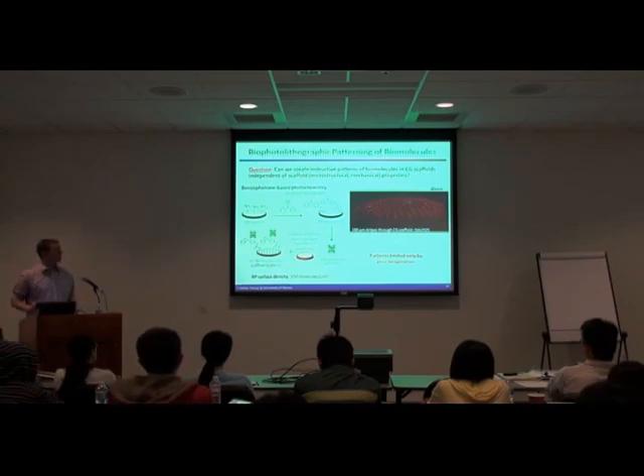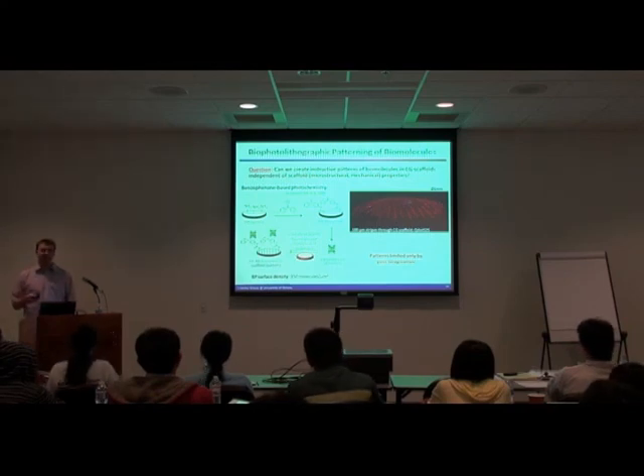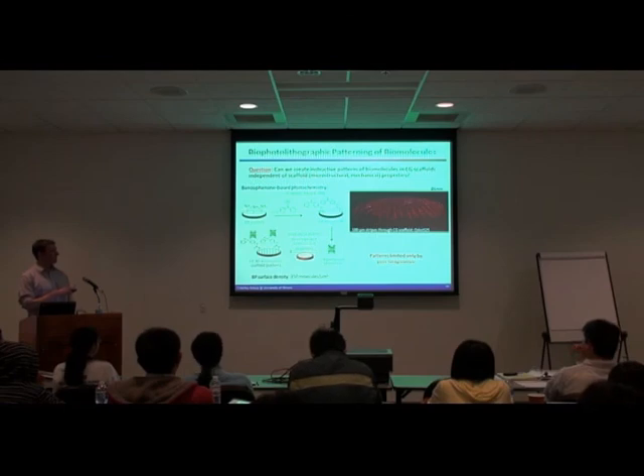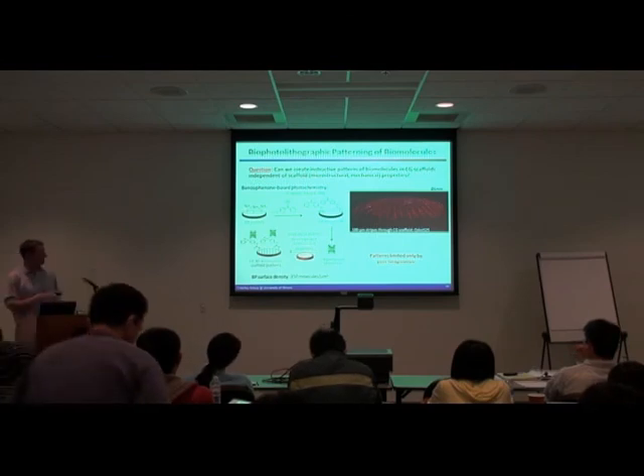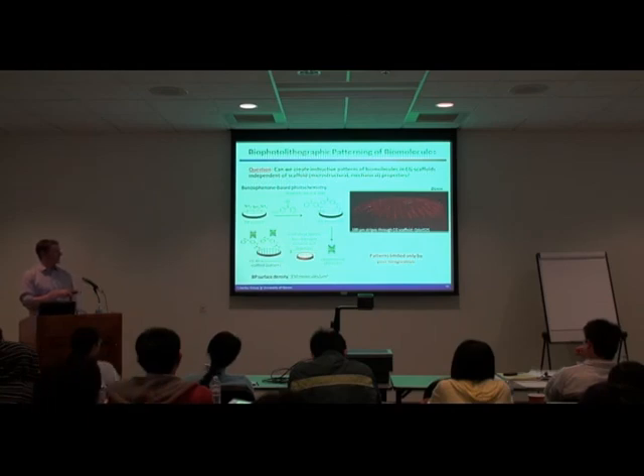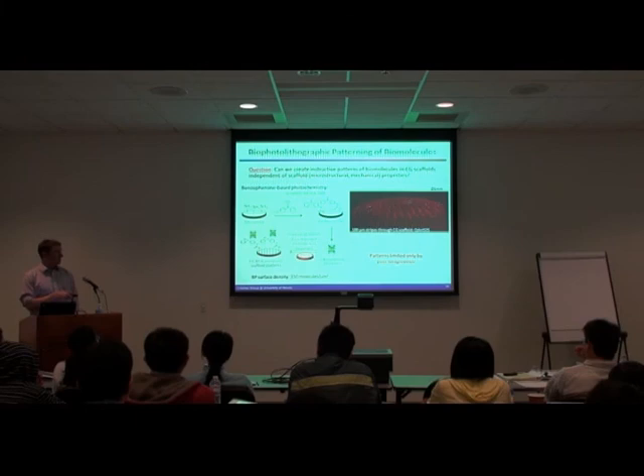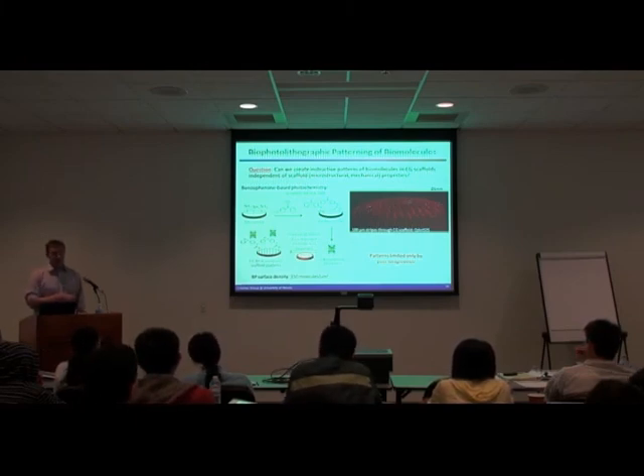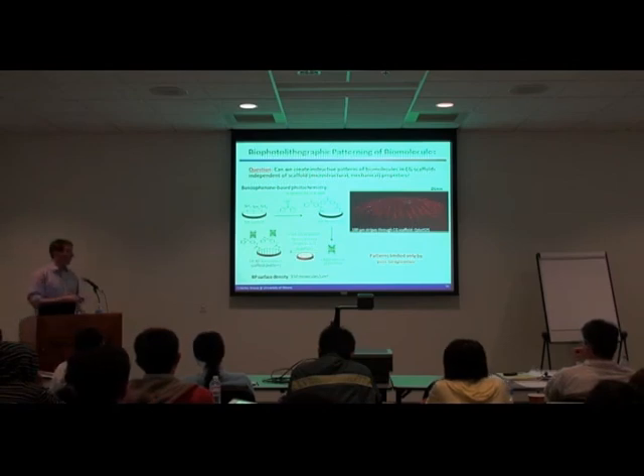This is the biomolecular aspect I didn't want to go into very much, but we can take our collagen GAG scaffolds and use a benzophenone photochemistry approach. We're working on this with a colleague here in Biomolecular Chemistry, where we take our scaffold with defined microstructure and mechanical properties, and attach onto the scaffold, through the free amines on the collagen surface, this benzophenone molecule. The interesting thing about benzophenone is that when you irradiate it at 365 nanometers, it forms this transient diradical, which will allow insertion into any CH bond. So you have some sort of biomolecule floating inside your scaffold, you hit it with UV light, and it attaches in the local region where the UV light is exposed, whatever biomolecule that is.